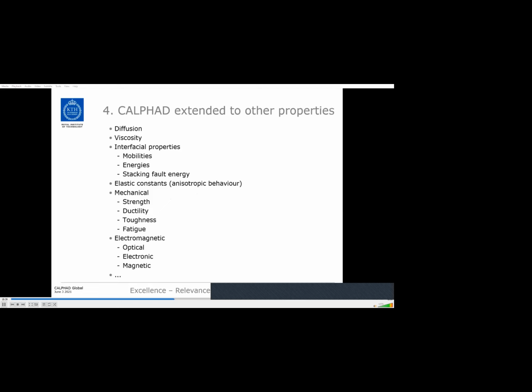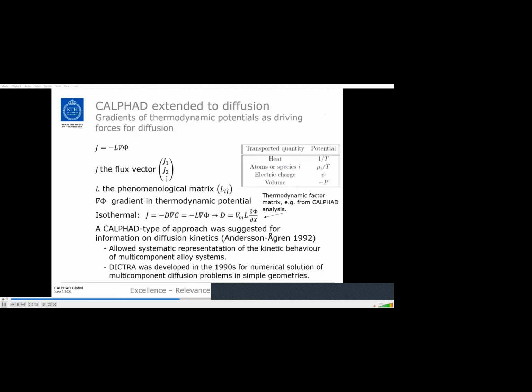I already mentioned extension to diffusion, but there are also extensions to viscosity, to interfacial properties, for example, mobilities, energies of interfaces, stacking fault energy, extension to elastic constant, anisotropic behavior, extension to mechanical properties like strength, ductility, toughness, fatigue, and to electromagnetic properties like optical, electronic, and magnetic, and so on. So CALPHAD extended to diffusion.